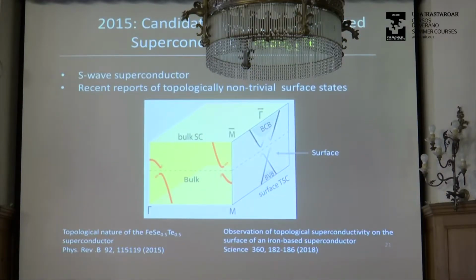However, recently there's been a new discovery. This is not a new superconductor, but it's a new discovery that this superconductor, iron selenium tellurium, with approximately this composition, although you can deviate a little bit, could have non-trivial surface states due to band inversion on one of the bands. Okay? So there are multiple bands crossing the Fermi energy, but one of the bands is band inverted, and due to band inversion, there might be topologically non-trivial surface states in this material.